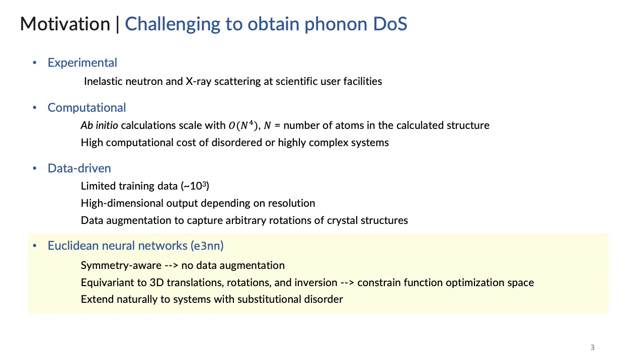Finally, data-driven methods face the challenge of currently limited databases of phonon densities of states available, with only 1 to 2,000 examples. This further makes it challenging to learn a comparatively high-dimensional output such as the density of states, which is a function of energy. Additionally, since crystalline symmetry is a key determinant of the phonon dispersion, encoding crystal structures is necessary, but simply using atomic coordinates means extensive data augmentation is needed to capture arbitrary rotations of crystal structures.